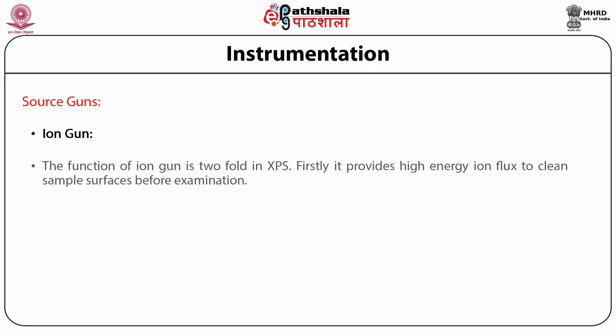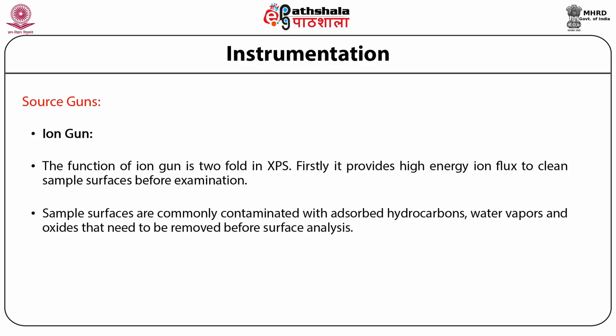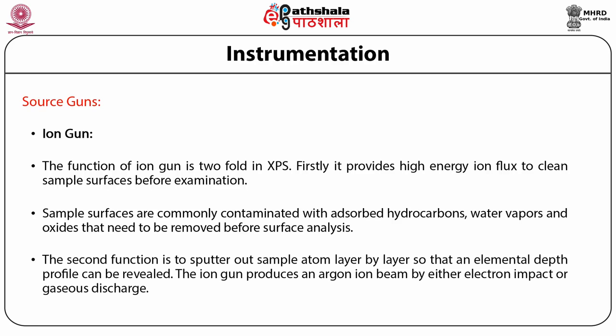Then the ion gun. The function of the ion gun is twofold in XPS. Firstly, it provides high energy ion flux to clean sample surfaces before examination. Sample surfaces are commonly contaminated with adsorbed hydrocarbons, water vapors, and oxides that need to be removed before surface analysis. The second function is to sputter out sample atoms layer by layer, so that an elemental depth profile can be revealed. The ion gun produces an argon ion beam by either electron impact or gaseous discharge.